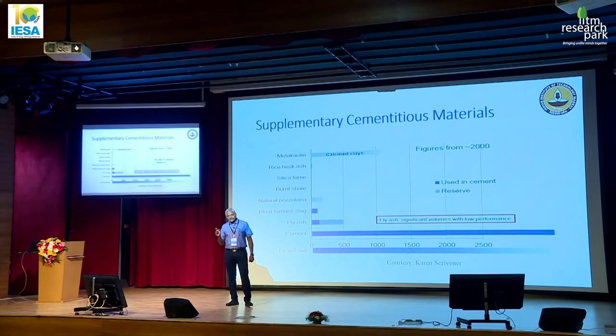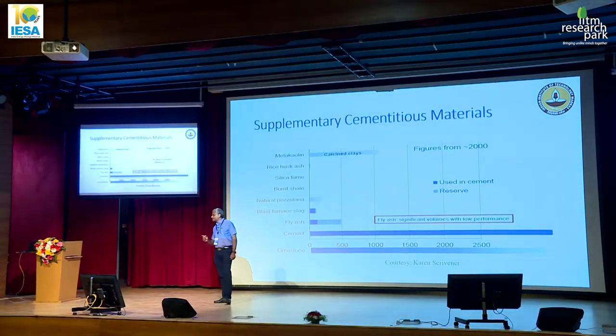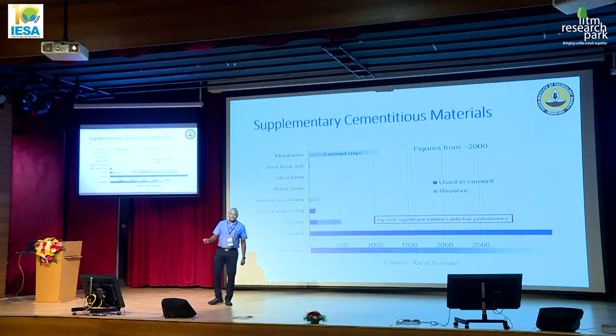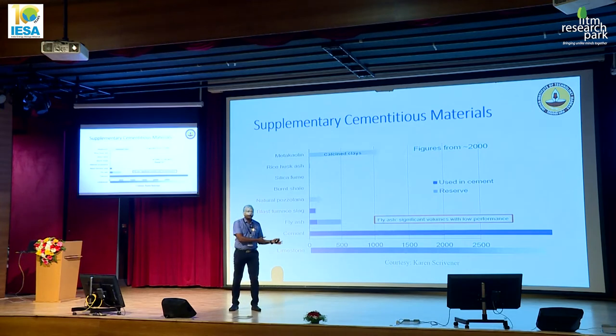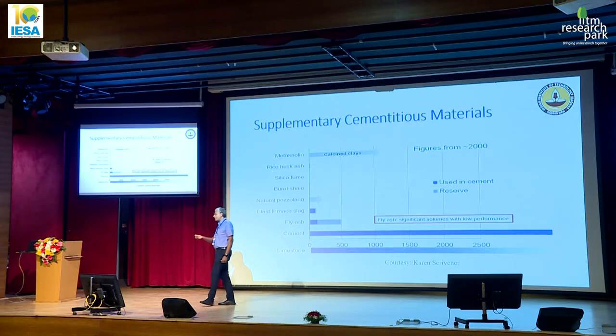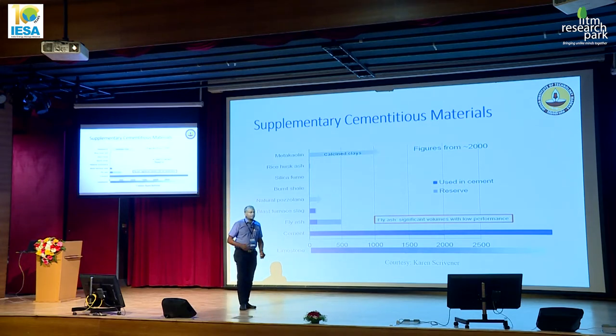right? Of course, in terms of quantities, the extent of slag that we have is limited as compared to the amount of fly ash. With fly ash, we have a lot of quantity available, but only part of it is actually usable because it's of a good quality. You may know that in thermal power plants, they have these ash ponds, right? They build very large ash ponds where all this extra ash that is not being sent off to cement manufacturers or to concrete producers is simply being slurrified and dumped. So there's a big environmental hazard there because those fly ashes do not meet specifications. They cannot be used in cement manufacture. And there's no other way but just to dump.